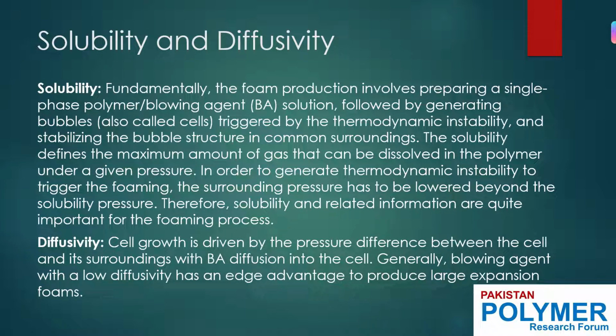So the solubility defines the maximum amount of a gas that can be dissolved in a certain polymer under a certain pressure. In order to generate thermodynamic instability to trigger the foaming, the surrounding pressure has to be lowered beyond the solubility pressure. Therefore, solubility and related information are quite important for the foaming process. Also, there are certain mathematical methods available to measure the solubility.